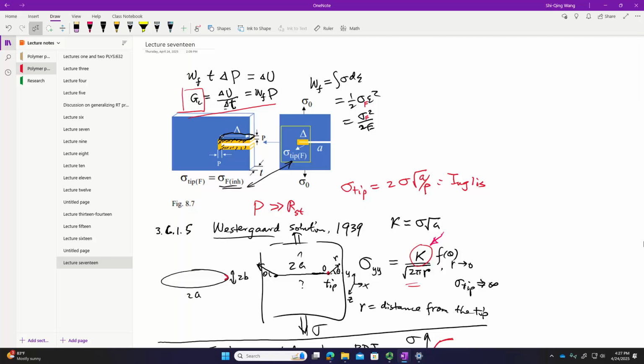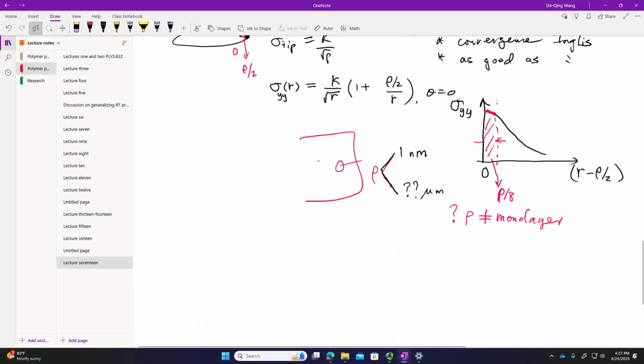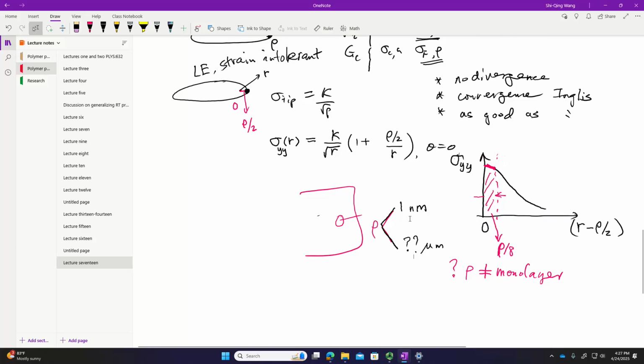When you reduce that rho to 1 monolayer, that's surface tension. But if this thing inherently involves a geometry that allows energy to store over a fraction of rho, and rho is not a monolayer, we just acknowledge for window glasses, it might be just a monolayer, because those bonds are so short-ranged and connected.